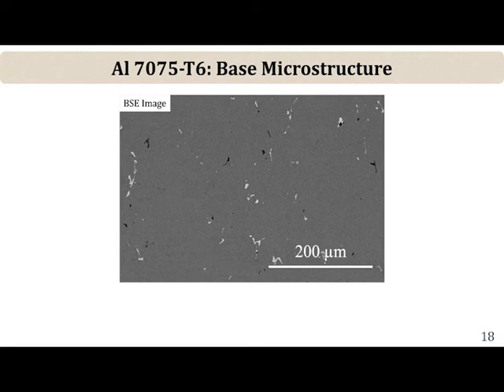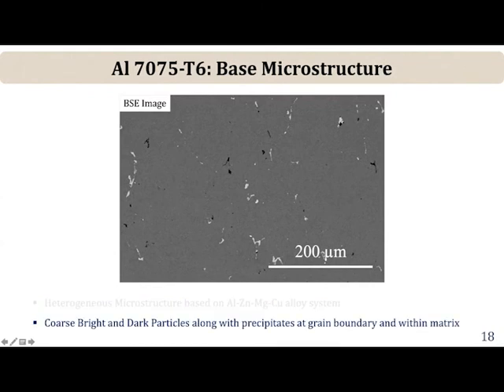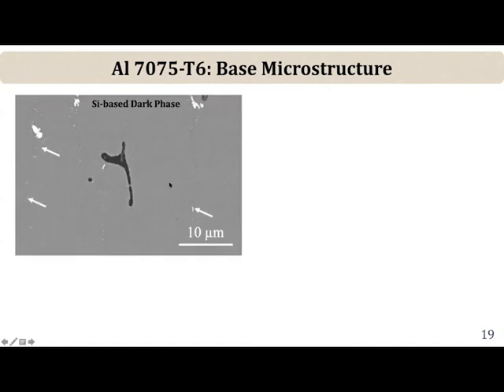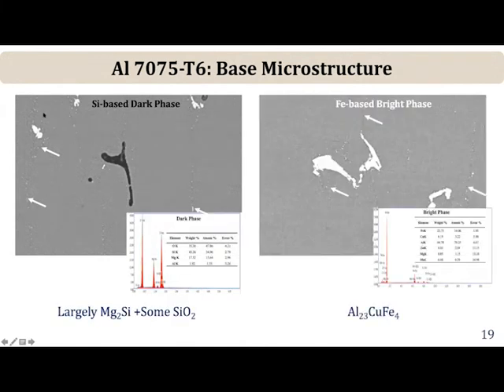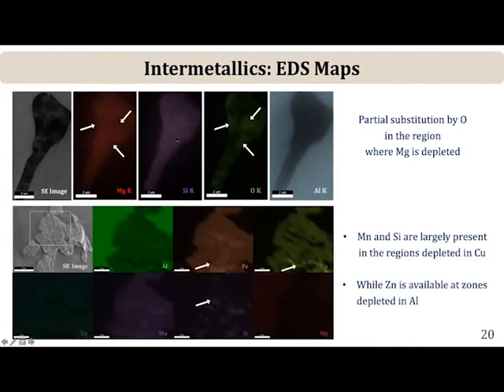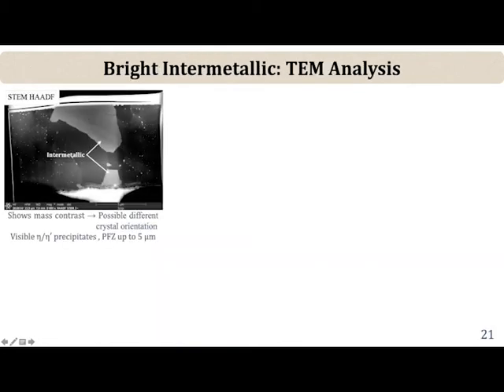Anyway, okay, so this is the base microstructure of the aluminum 7075-T6. Basically, you see two kinds of intermetallic particles, bright looking particles here and darker looking particles. The darker looking particles, you see these are basically magnesium silicon or even can contain higher levels of oxygen. These brighter particles here are aluminum iron copper. And then you also have some brighter particles along subgrain boundaries and along grain boundaries. When you do these EDS maps, you can see that some of these particles are basically magnesium silicides or even magnesium silicate. The other, we FIBbed out an area where we could FIB out a particle itself.